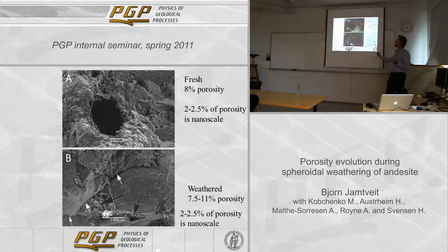But even more surprising, there is an enormous amount of really tiny ones. When we injected mercury to have an independent measure of the porosity, we got a mercury porosity that was much smaller than the helium porosity, meaning that a lot of the pores or pore throats were so narrow that you couldn't get mercury in.